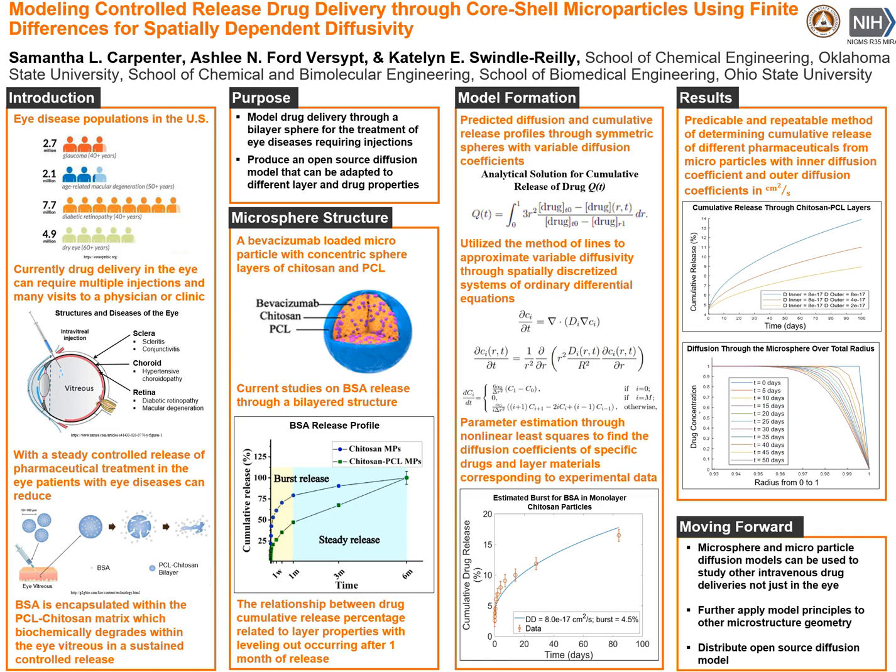months. In our model, we used a symmetric sphere with variable diffusion coefficients with an analytical solution you can see at the top. This solution shows the release of drug Q with respect to time is integrated over a non-dimensional radius 0 to 1. We then utilize the method of lines to approximate variable diffusivity of the two layers through spatially discretized ODEs.